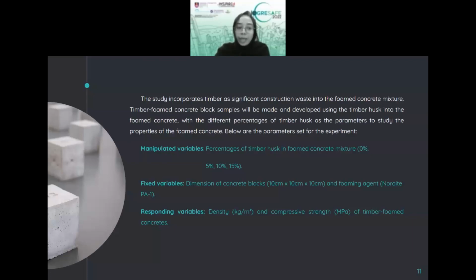And the foaming agent, I use a protein foaming agent for the concrete mixture, which is the Noraite PA1. So for the responding variable, I will be testing the density and compressive strength of the timber concrete for different curing periods, which is on the 7, 14, and 28 days of curing period, and also after I submerge the concrete into the seawater.